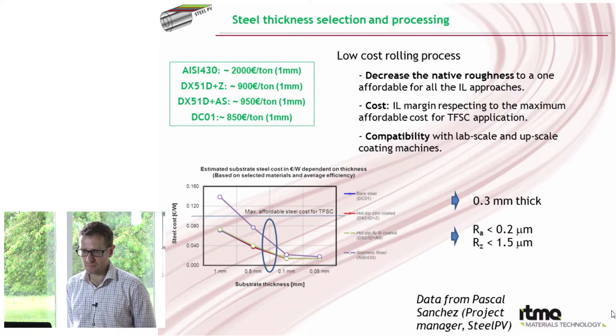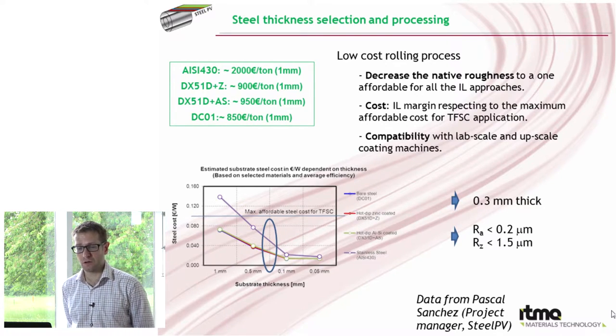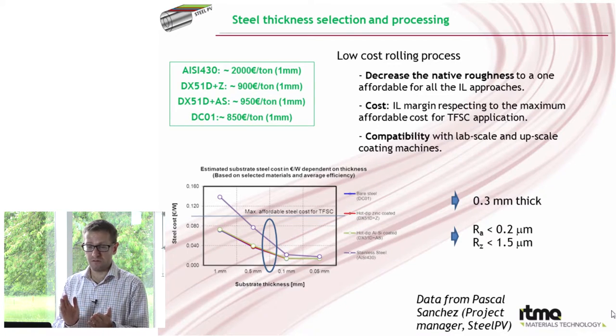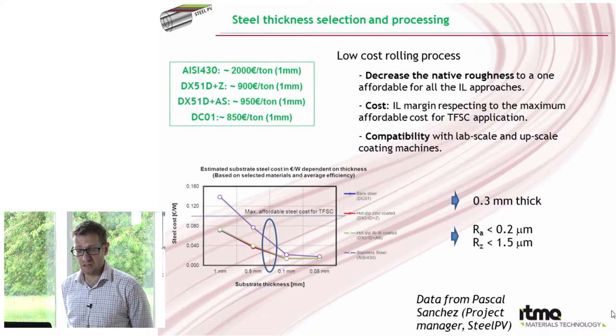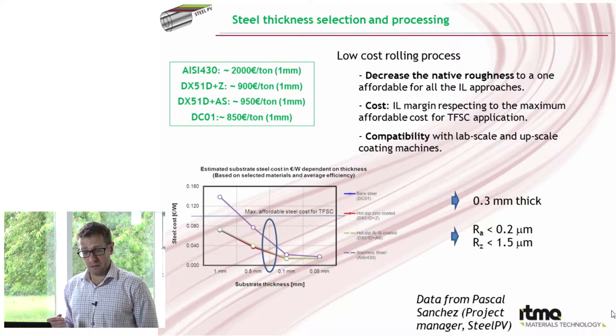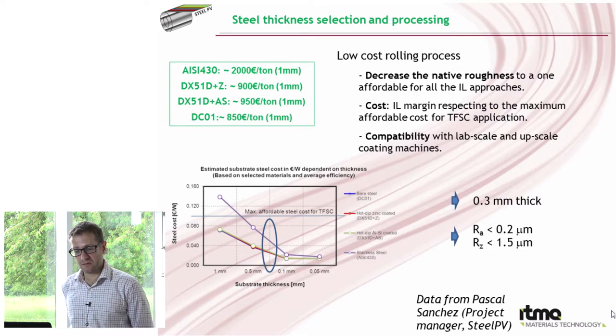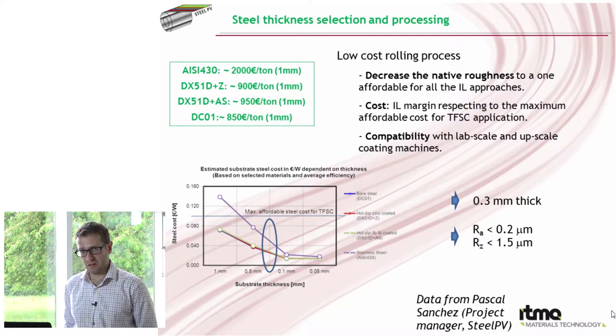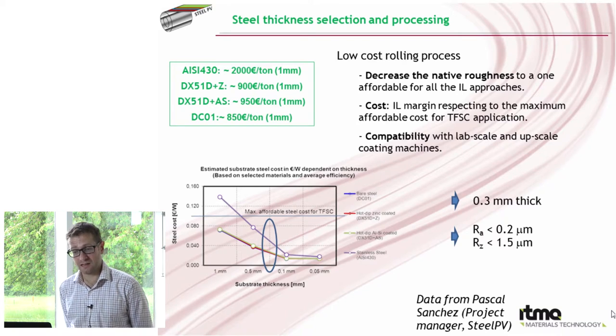Now with all of these steels, what we tend to do is roll the steel. So we use a low cost rolling process, which allows us to first of all decrease the roughness of the steel, but also reduce the thickness, so we can use steel sheets for production of solar cells. What we've identified is an optimum thickness. So if we can take the thickness down to around about 0.3 millimeters, then the cost of that steel substrate, assuming that the solar cell gives around about 10% efficiency, can be less than 0.1 euros per watt.